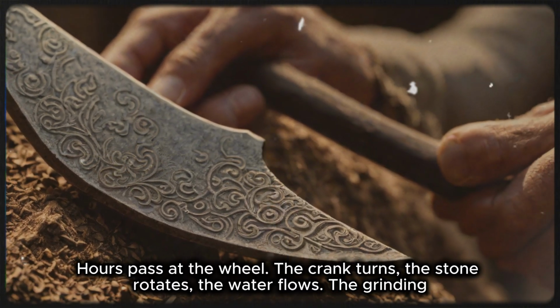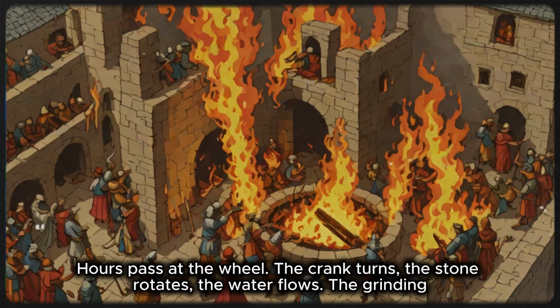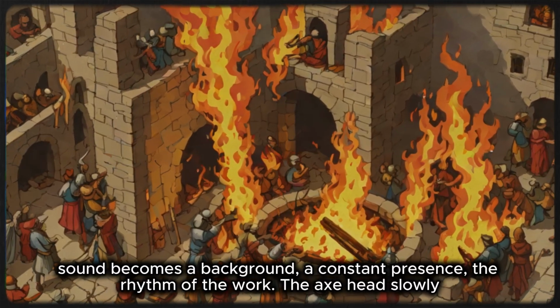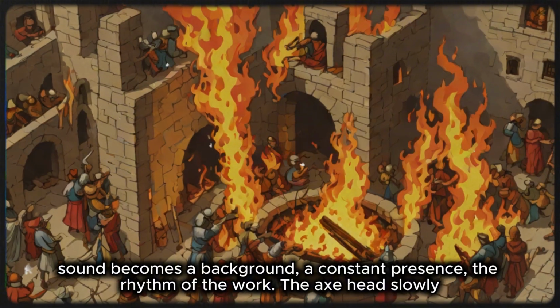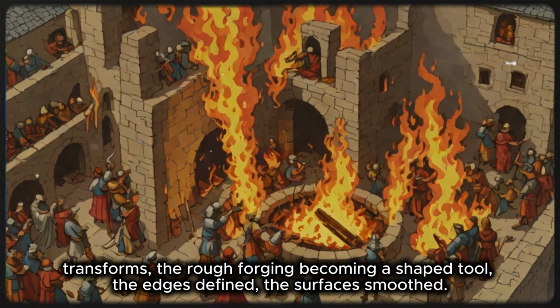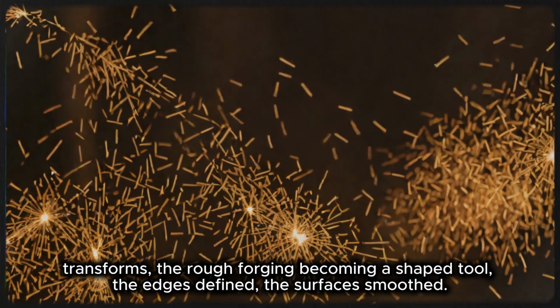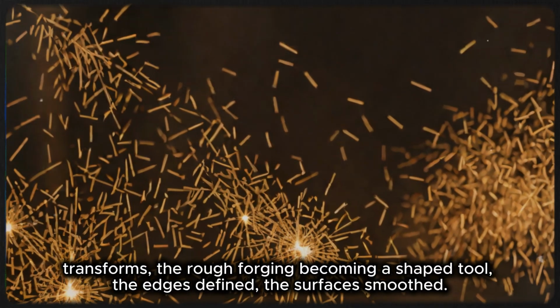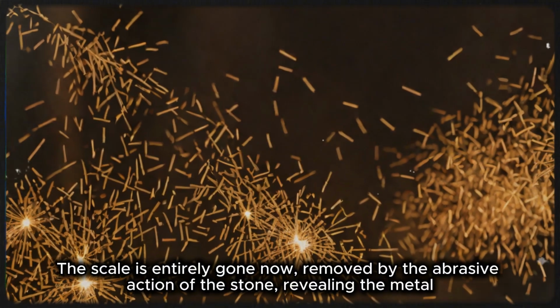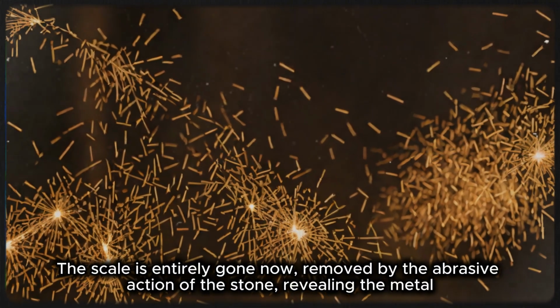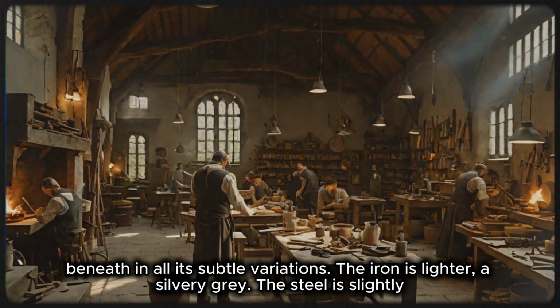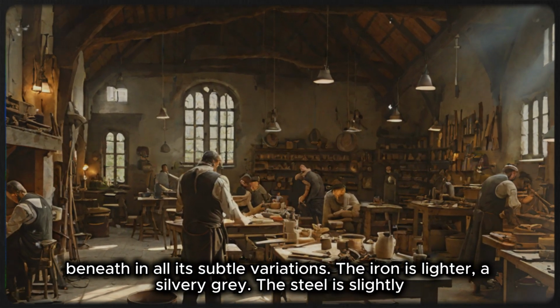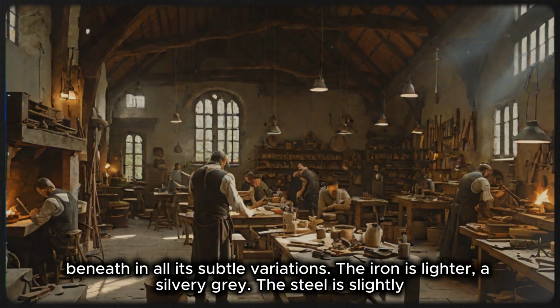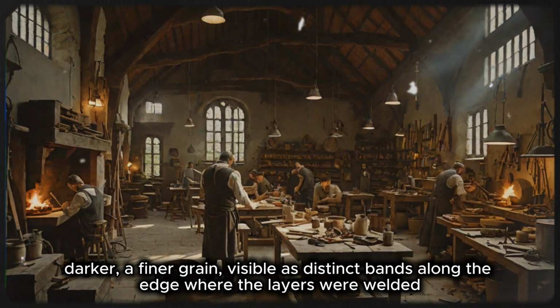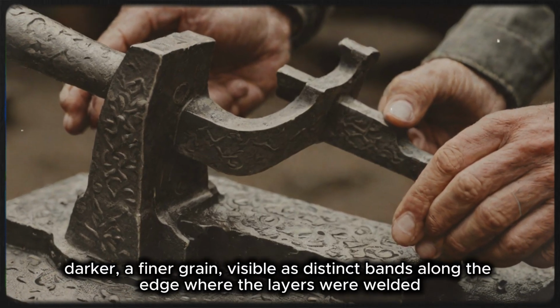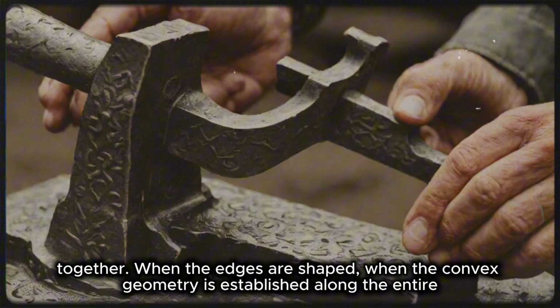Hours pass at the wheel. The crank turns, the stone rotates, the water flows. The grinding sound becomes a background, a constant presence, the rhythm of the work. The axe head slowly transforms, the rough forging becoming a shaped tool, the edges defined, the surfaces smoothed. The scale is entirely gone now, removed by the abrasive action of the stone, revealing the metal beneath in all its subtle variations. The iron is lighter, a silvery grey. The steel is slightly darker, a finer grain, visible as distinct bands along the edge where the layers were welded together.